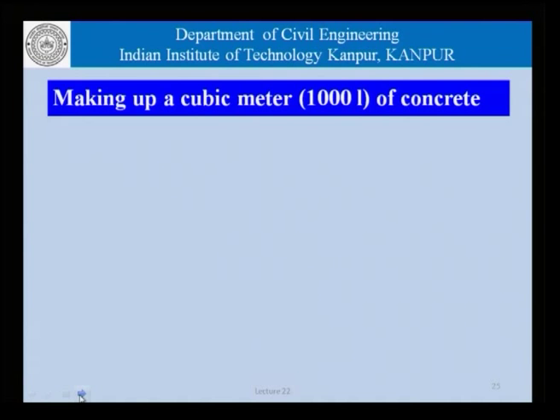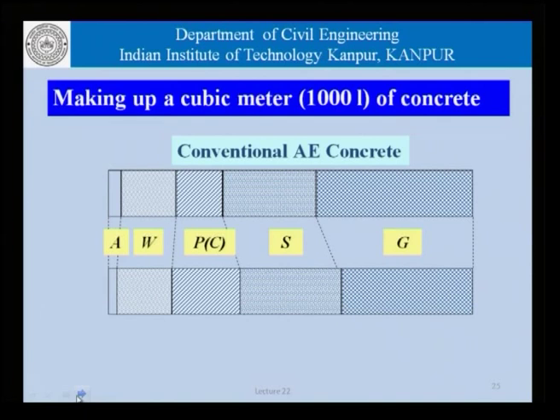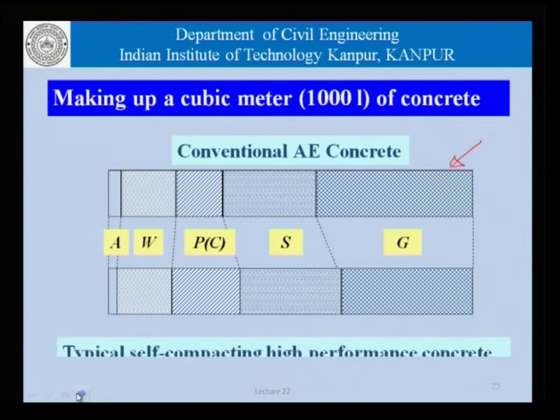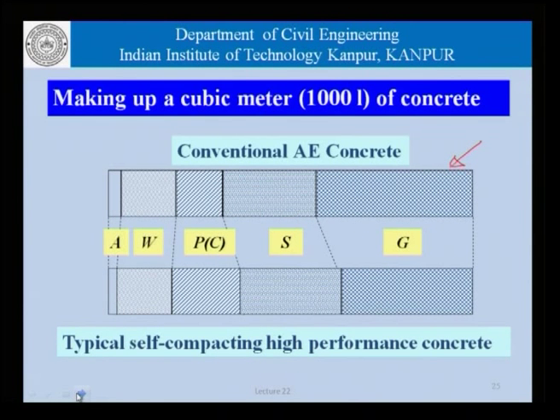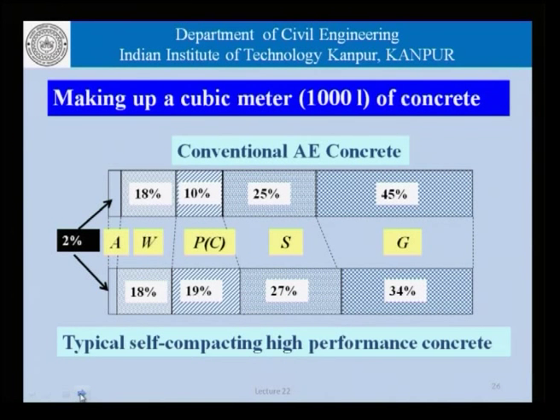Now, if this data was converted to a volumetric chart, which says that air, water, powder or cement, sand and gravel, this here is the distribution as far as normal conventional air entrained concrete is concerned, and the picture below is that of a typical self-compacting high performance concrete. Now, if we look at the numbers, in both cases we can assume that the air content is not really different, it is the same 2%, water is about the same.